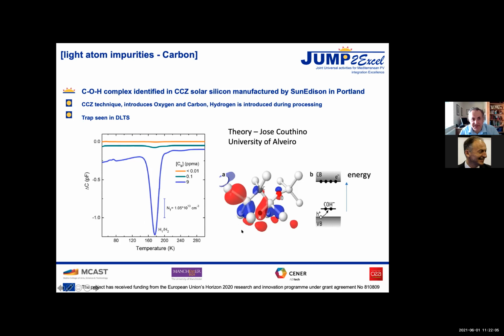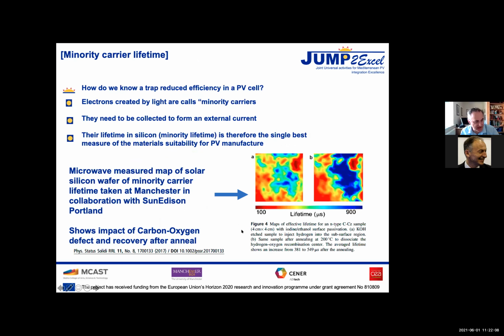What was the impact on the cell material? Well, how do we quantify the impact it has on the cell? Well, what people working in solar PV worry a lot about, or think a lot about, is what we call minority carrier lifetime. What this means is when a photon from the sun creates an electron, if it's in p-type silicon, which is what's used as the absorber for 95% of solar cells currently, that electron is a minority carrier. There's less of it around than there are holes. And we have to collect that at the contact. And if we don't collect it, that's a loss. And so what we can measure or define is something called a minority carrier lifetime. And that's how long the electron will exist in this p-type silicon before it recombines with a hole, either naturally through something like Auger or by the presence of a defect.